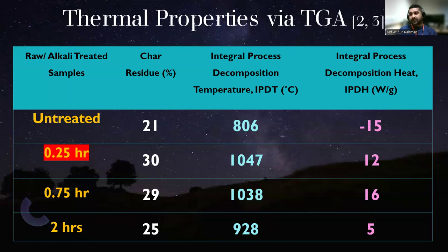So in general, conventionally, we look at the weight with the temperature, from the onset temperature, or maybe the high peak temperature. Some references even suggest that, like, 15% mass loss or 75% mass loss, from that we can say whether it is more thermally stable or not. So IPDT is one of the ways. Instead of those peaking points, it collectively collects all the scenarios in the whole event, so it is a holistic representation. We found that this value is proportional to the char value. For example, if the char value is higher, this value would be higher, but this is a representation with the temperature.